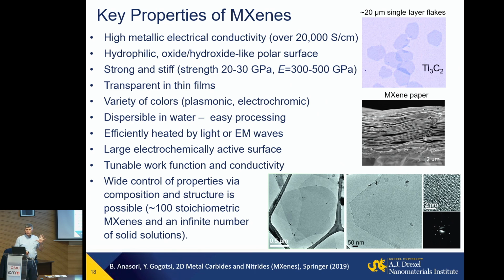For people who don't know, if you work with graphene, you make graphene oxide, you reduce it, you will get at maximum 2 to 4,000 Siemens per centimeter. We get 10 times more without any reduction process and without any post-treatment. So it's 10 times more conducting than reduced graphene oxide, and hydrophilic like graphene oxide. So it's a very unusual combination. You basically can make a metallic clay or water dispersible metals.